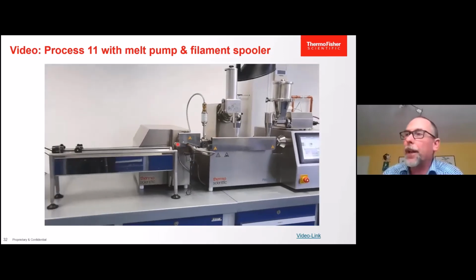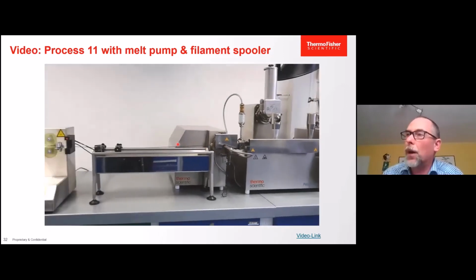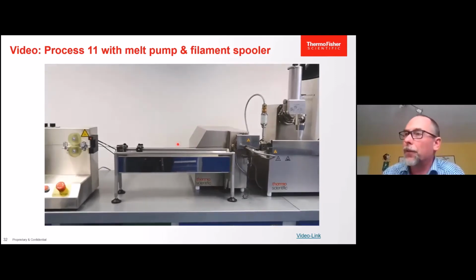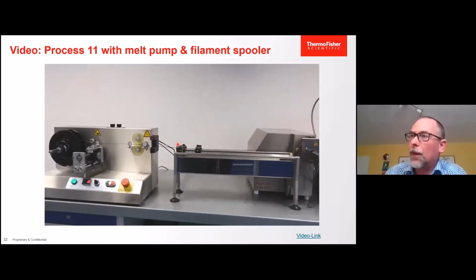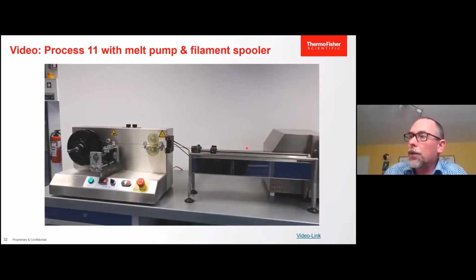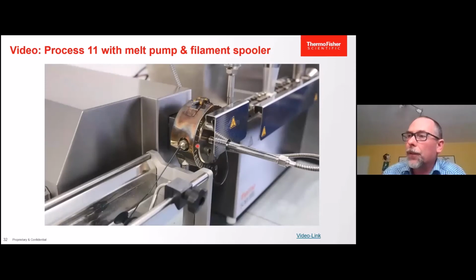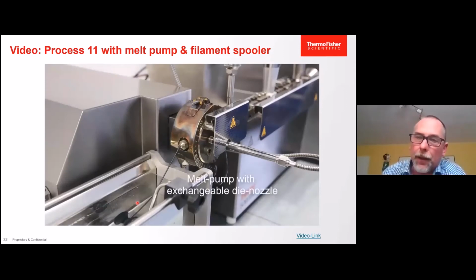The melt temperature actually will result by the compounding and the introduction of energy to the system. Going further down through the melt pump, an even strand is taken off. It runs into a water bath. We can change actually the nozzle diameter to fit the strand diameter.